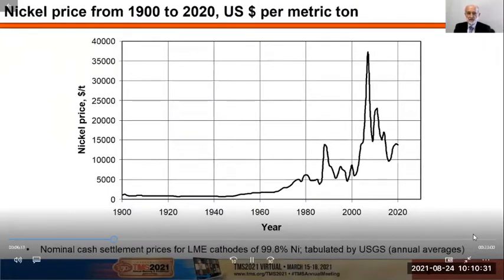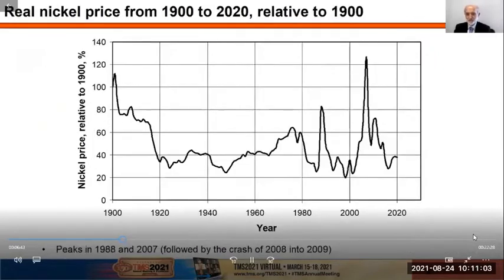The nickel price is shown for that same time period. And of course, that has varied quite considerably over more than a century. The figures shown here represent the nominal cash settlement prices for LME cathodes of 99.8% nickel. It's also important to note that the figures have been tabulated as annual averages to remove some of the fluctuations. However, you can see that nickel prices certainly fluctuate an awful lot.